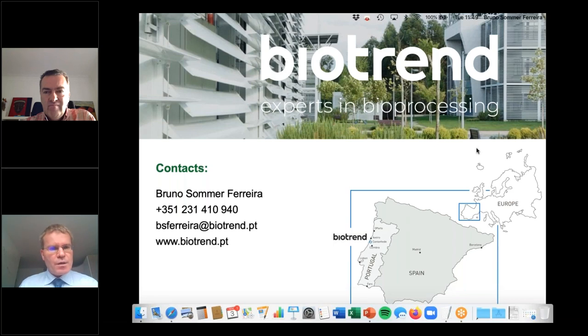Thanks. And then you have one more question, Bruno, from Slavomir Sizielski. You showed the comparison of PHA synthesis using pure VFAs and permeate. Was the composition of the pure VFA mixture the same as in the permeate? It was quite comparable, yes, because before we decided on which mixtures to use in our mock trials, we did consult with OWS, which provided us the range of specifications that was expected in the real operation. And so all the prior trials were performed taking that information into account, which proved to be quite accurate in the end.